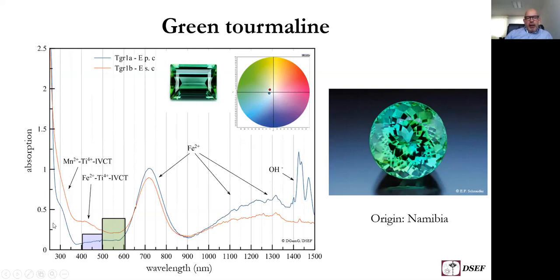We look here at the absorption, and this is a spectrum that shows the absorption between 250 and 1500 nanometers, so from the ultraviolet until the infrared. Now we're only interested in the visible light range, roughly between 300 and 700 nanometers. And here you see the corresponding plot of these spectra in the CIELAB color circle. When we look at the red spectrum, we see first of all a prominent absorption band of iron at around 720 nanometers, which absorbs the red part of the spectrum. And we see another small band at around 400, with a maximum at around 420, which is due to iron-titanium charge transfer. This causes an absorption minimum, or transmission maximum, in the green part of the spectrum.